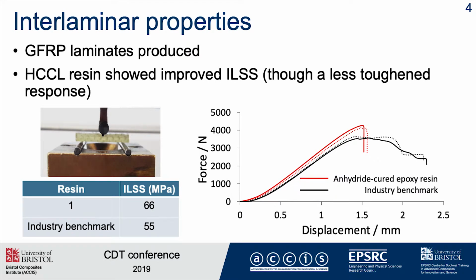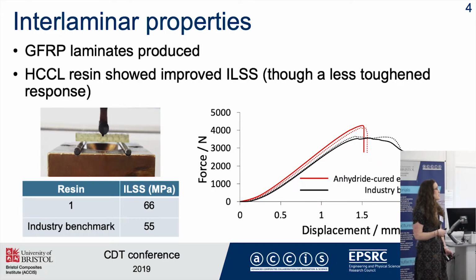So I then looked at the resin interface. At the minute, the resin is on glass fibre. So I should take a step back. I did 3-point bend, short beam shear, to look at interlaminar shear strength, and we found that the anhydride resin is better than an industry standard amine cured epoxy resin on glass fibre. And although the amine does show increased toughness, we're not looking at that at the minute.